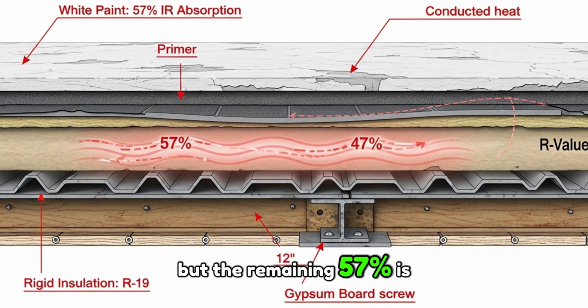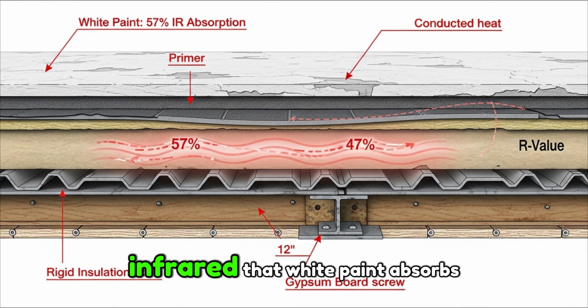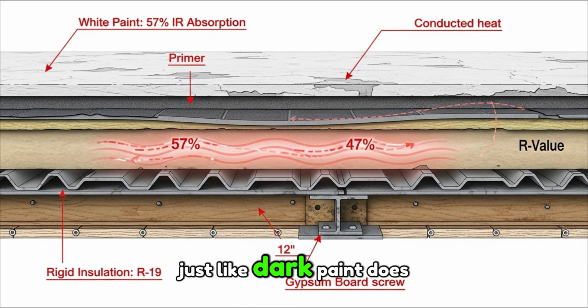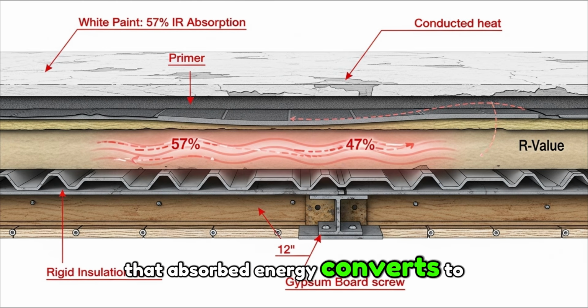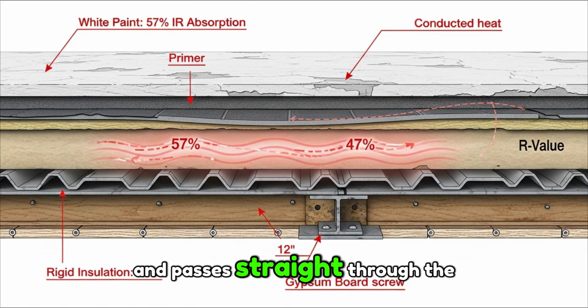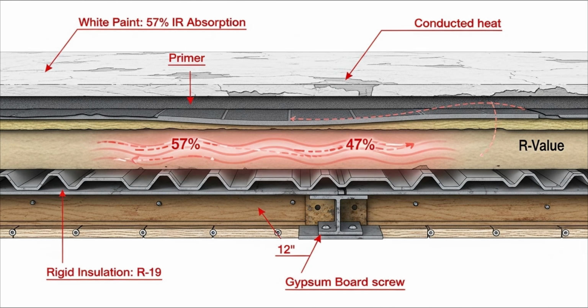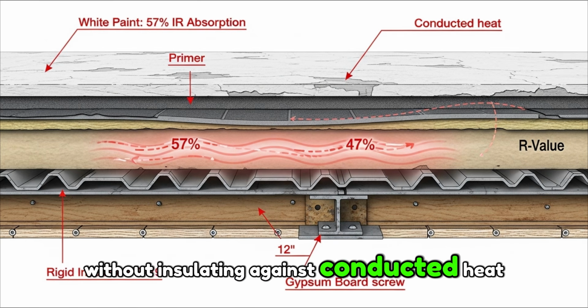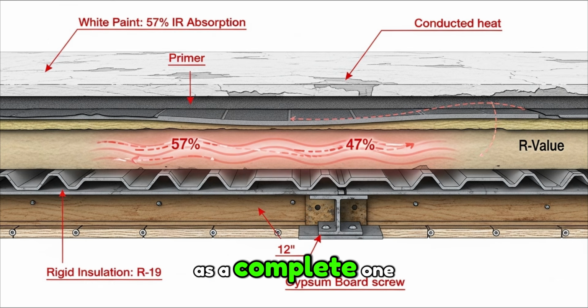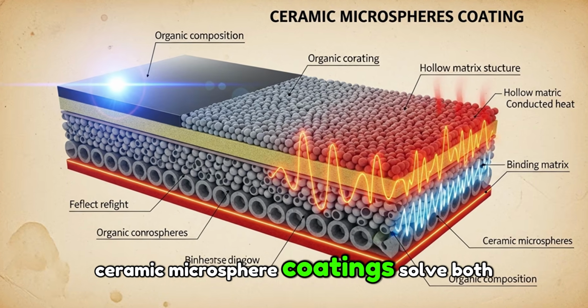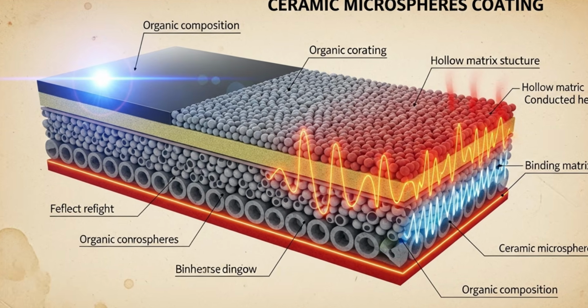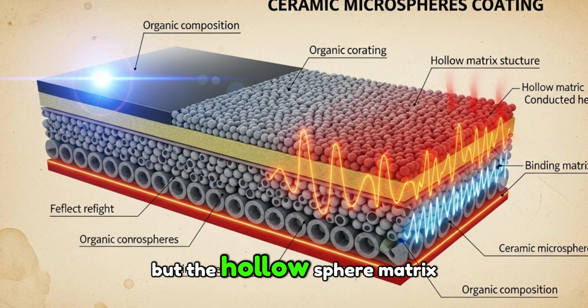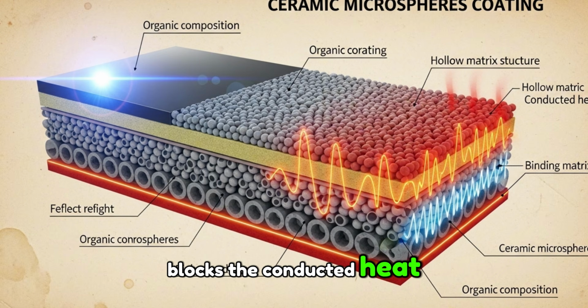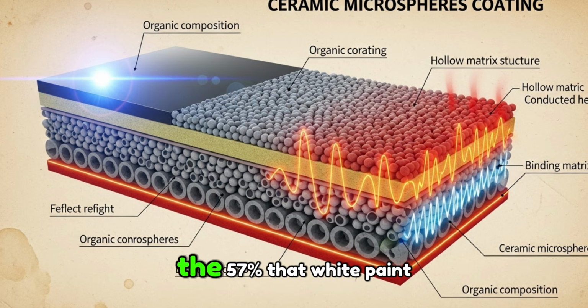But the remaining 57% is longer wavelength infrared that white paint absorbs, just like dark paint does. That absorbed energy converts to conducted heat and passes straight through the paint film into your roof deck underneath. Reflecting light without insulating against conducted heat is half a solution marketed as a complete one. Ceramic microsphere coatings solve both problems simultaneously. The surface reflects visible and near-infrared energy the same way white paint does, but the hollow sphere matrix underneath blocks the conducted heat from the absorbed infrared radiation, the 57% that white paint lets through untouched.